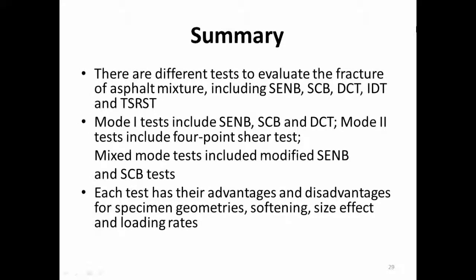So here comes my summary. In this presentation, I summarized there are different tests to evaluate the fracture of asphalt mixtures, including the single notch SENB, SCB, DCT, IDT, and TSRST tests. For the mode 1 test, we have the SENB test, SCB test, and DCT test. And for the mode 2 test, we have the 4-point shear test. For the mixed mode test, there will be a modified SENB or SCB test.